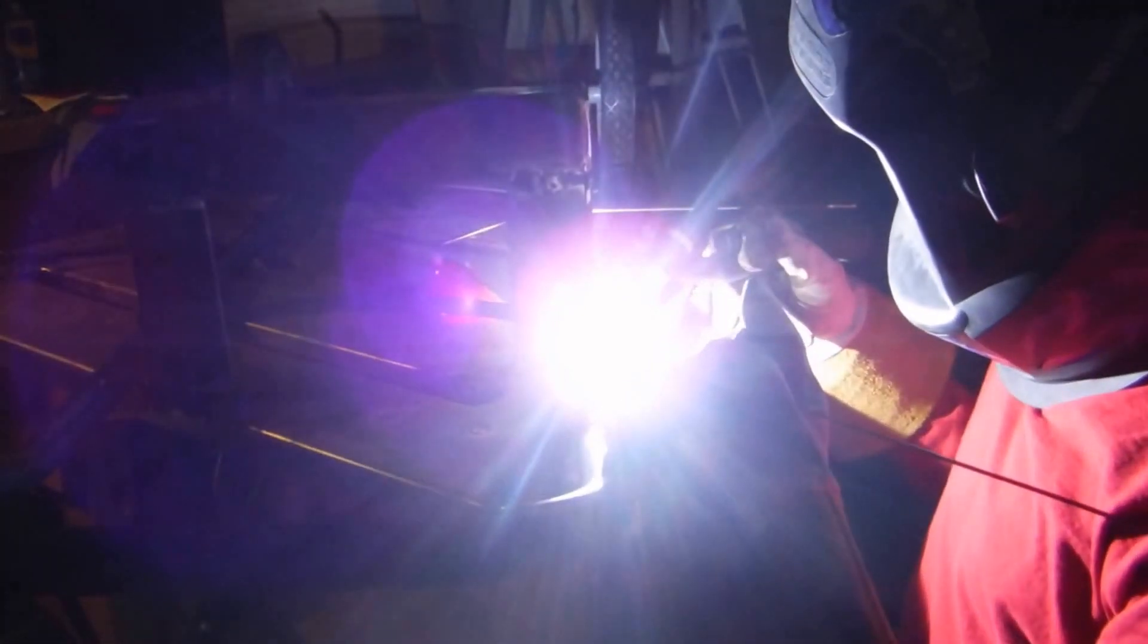Okay, it is tacked in place. I'm going to weld out both sides of it. And then we're going to put the welder on it and just strap it down. So I'm going to weld out this side first. I'm going to turn it up to 50 for welding. I'm going to use a 1/16th diameter rod, just because it gives me a little more feel and control. I am favoring the arc on the thicker piece.